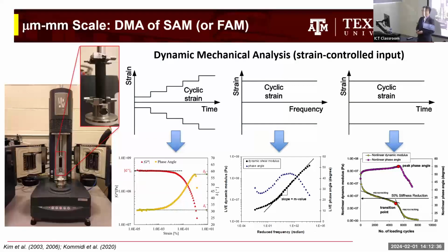Regarding micrometer to millimeter scale, which is one of my PhD thesis topics, like DMA, dynamic mechanical analysis of sand asphalt matrix, or FAM, fine aggregate matrix. Some of you are familiar with what I'm talking about. We tried to develop a methodology that can characterize fatigue cracking, healing, damage accumulation, and things like that from the binder level or matrix level. You can see some experimental data nicely representing the behavior of the material, like viscoelasticity and damage evolution, from this methodology. It was pretty successful, from these efforts back in the early 2000s and later on.